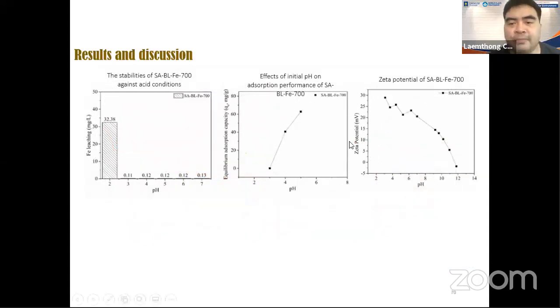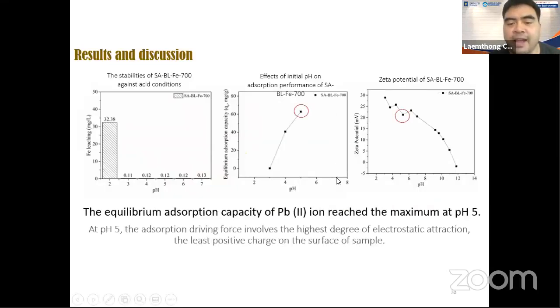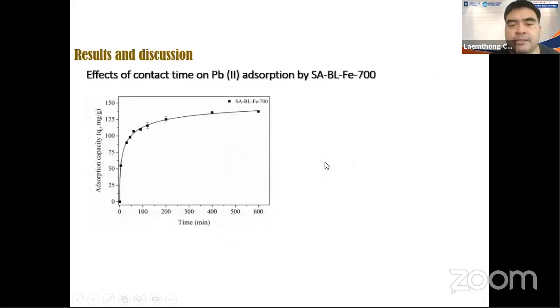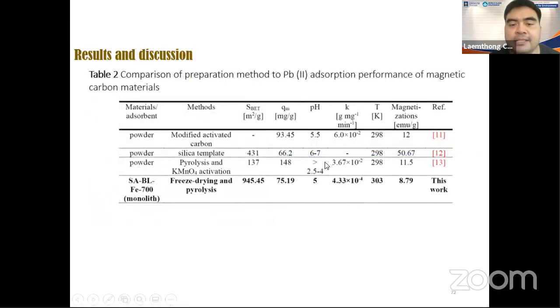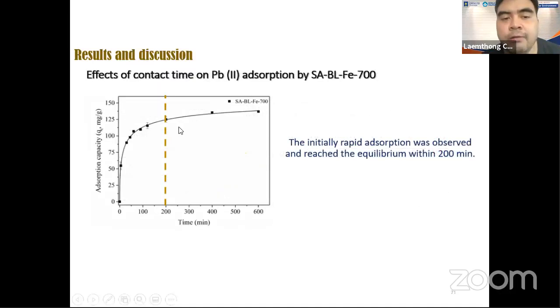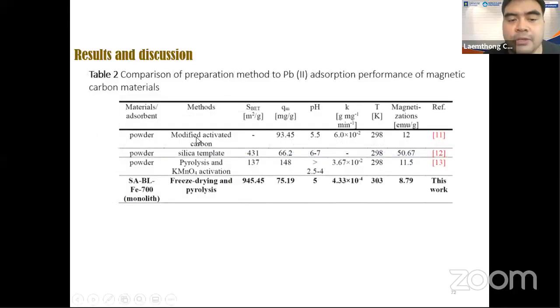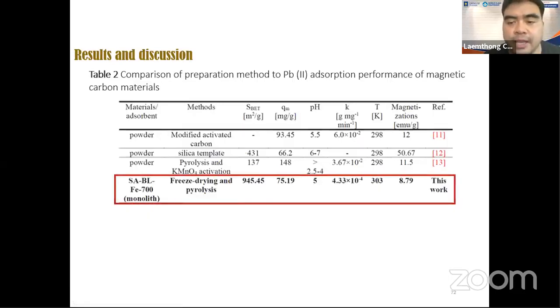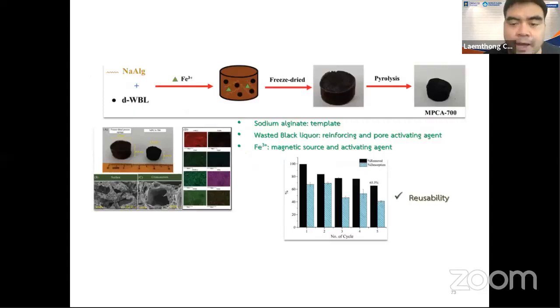So we checked the performance of interacting with the lead ion, which is quite a toxic chemical in our environmental system. And we can see that, because of our hierarchical structure, the contact time to adsorb the maximum amount of ions is quite small. That means it's quite fast adsorption in this case compared to other work, which seems to be more complicated and also uses other toxic chemicals. So that means our work seems to be quite nice.